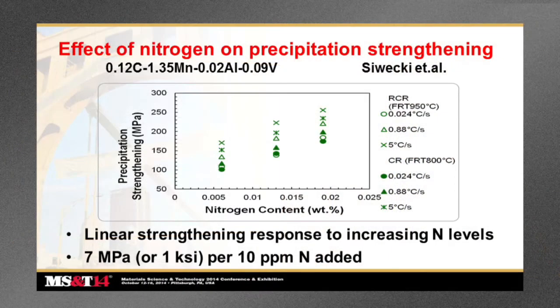Subsequent to that work, there's been much more work. I will refer to the work by Siwecki and others on nitrogen, the effect of nitrogen on precipitation strengthening. In this case, a 0.12 carbon, 1.35 manganese material, as you see, with aluminum and 0.09 vanadium. In that case, the graph clearly showed that there was a linear strengthening response to the increasing nitrogen levels, and that this slope was consistent with different processing variables,